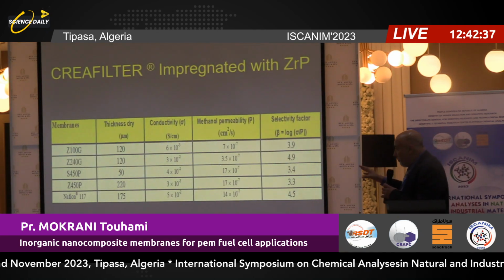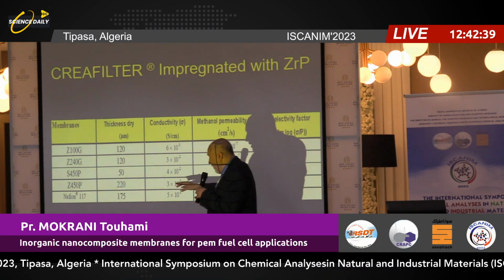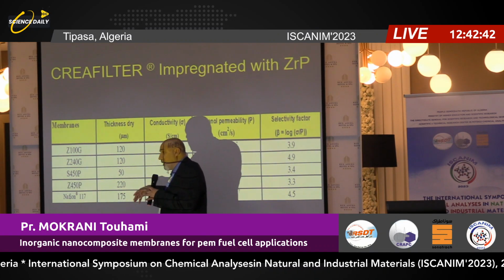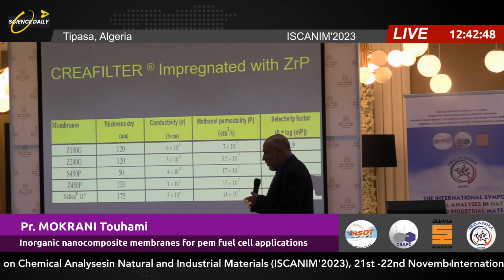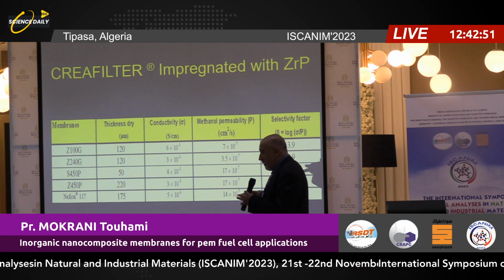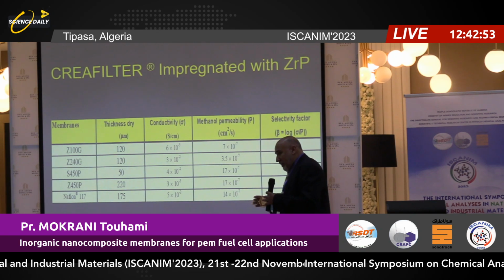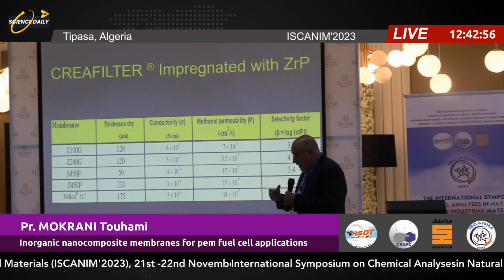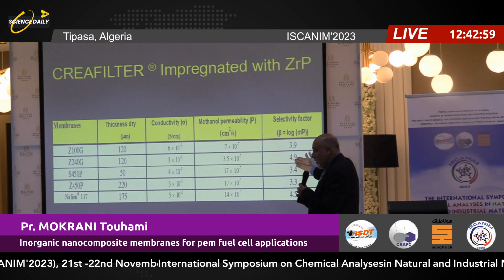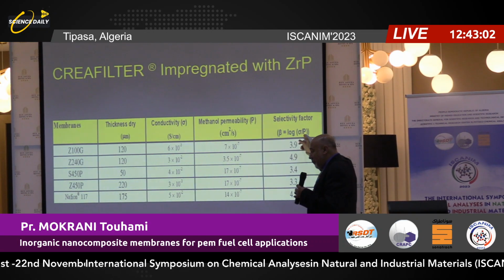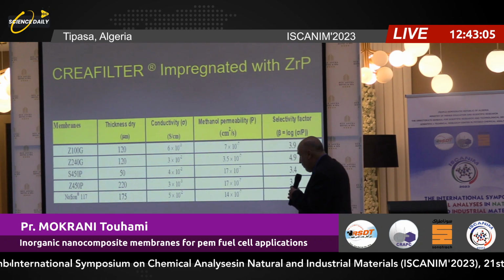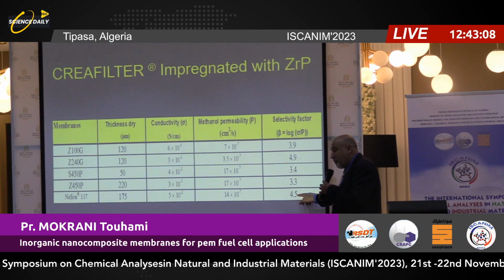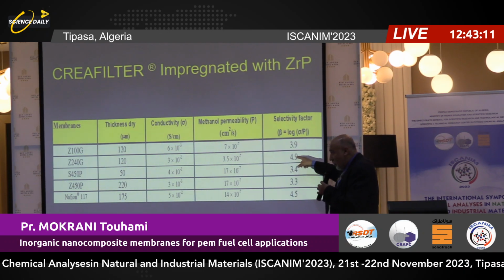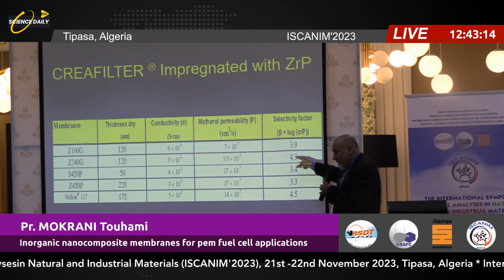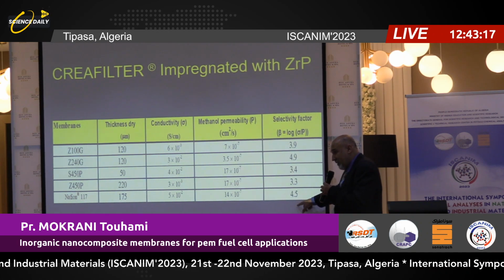So here, all the membranes, we can see the characterization. As I said, the thickness is very important because the thicker the membrane is, the less methanol going through, but less conductivity. So you need to balance between conductivity and methanol permeability. And to get an indication about the performance in a real fuel cell, you can see the selectivity factor, which is conductivity divided by permeability. So the reference, Nafion 117, is 4.5. So anything above this is better. So we can see this one is better. It's supposed to perform better than Nafion 117, the reference.